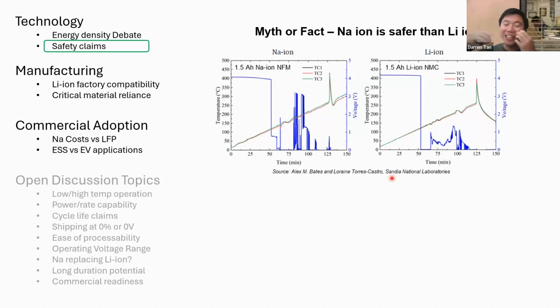Now, because there are no 2 chemistries with the exact same energy density, you will never get both to be the same. One will always be smaller or lighter, or if you force them to be the same shape, one will always have a higher capacity. But what these guys did was they took a commercial sodium-ion battery and they deliberately built a lithium-ion battery with lower energy density to match the sodium-ion capacity. So we end up having a very nice apples-to-apples comparison.